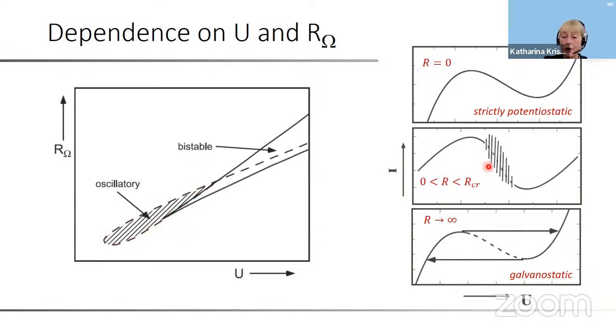The oscillations occur under conditions where the system is not yet bistable and occur around the branch of negative differential resistance. Note that these N-NDR oscillators never oscillate under galvanostatic conditions. So under galvanostatic conditions, you're always back to the bistable region. But of course, there are many systems which oscillate under galvanostatic conditions. And I will come back to this mechanism in a moment.